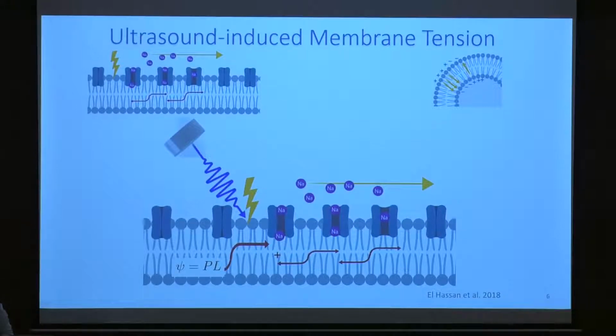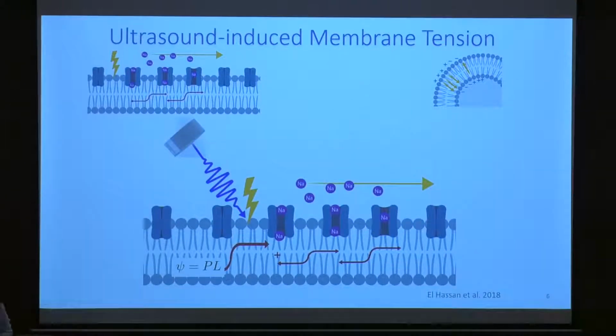As for the ultrasound-induced membrane tension, we know that the ultrasound basically causes a tension force in the membrane where it is applied. As you notice, there are two different arrows in this figure. One has a bigger dimension because the effect of the ultrasound tension is actually greater than the effect of the tension caused by the variation of the potential across the membrane.